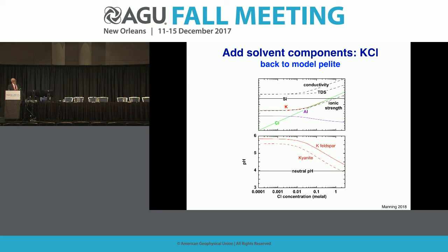And notice that the total dissolved solids go up, and finally that the conductivity at the very top of the upper panel also goes up. An interesting aside here is that by having these salty solutions, the pH is neutralized from the alkaline conditions that I went on at length about before to something a little more neutral, and in fact at very high concentrations of potassium or sodium chloride, these brines may actually be somewhat acidic.